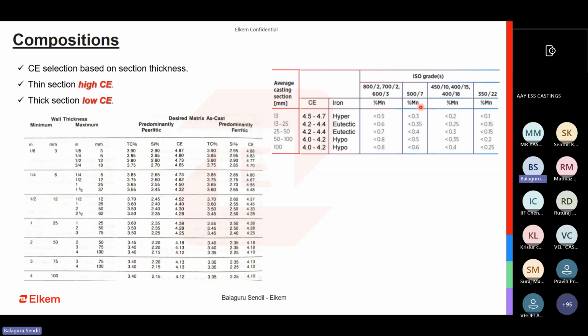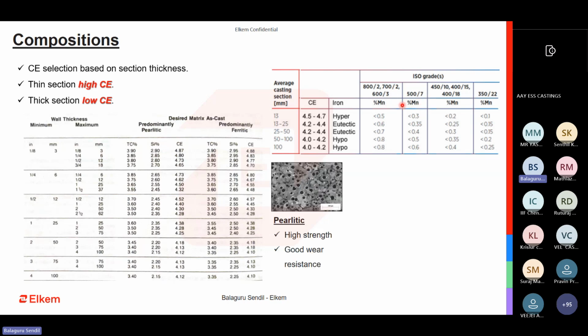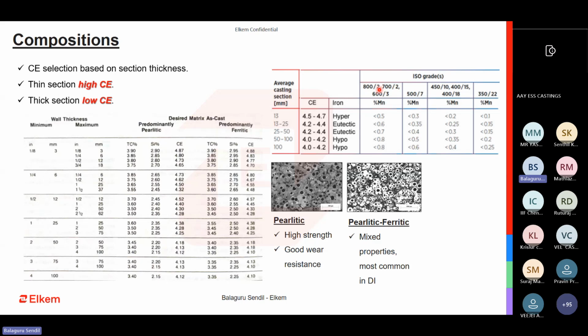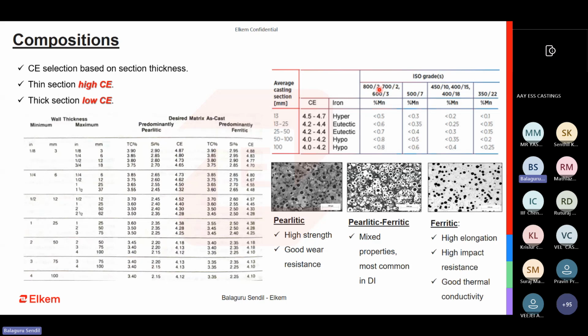It is with respect to the alloying elements. So we have perlitic grade, which has very high strength and good wear resistance, basically high strengths like 800 bar 2, 700 bar 2, 600 bar 3. And then we have a mixed matrix of ferrite and perlite, and then you have very ferritic grades. The ferritic grades have very good elongation and impact resistance, good thermal conductivity, but they do not have very high strength. They are quite soft, but at the same time more elongated, malleable.